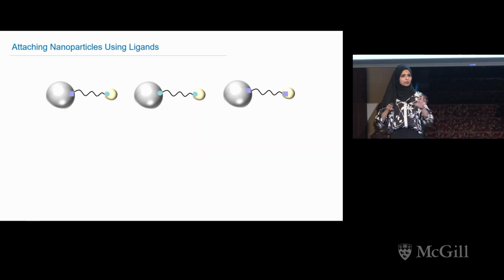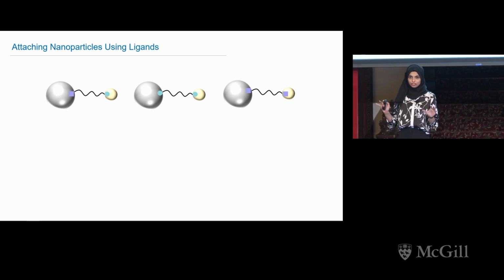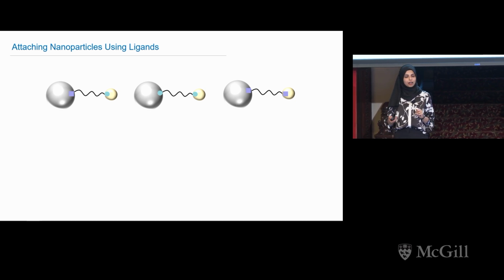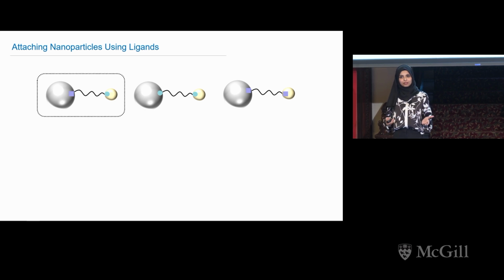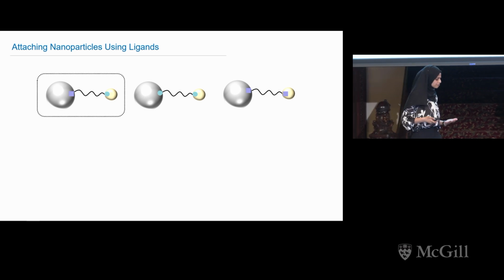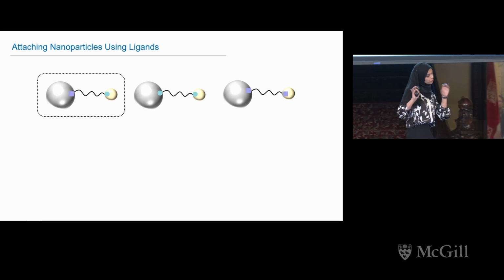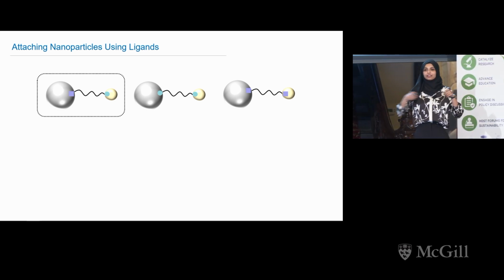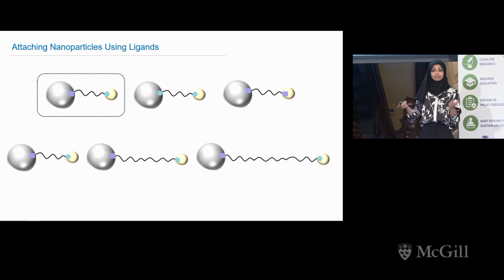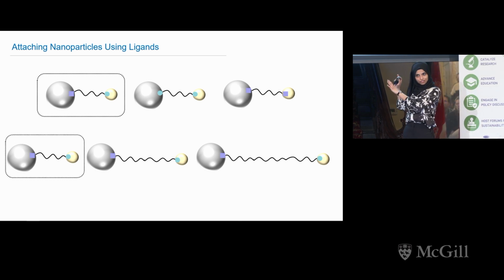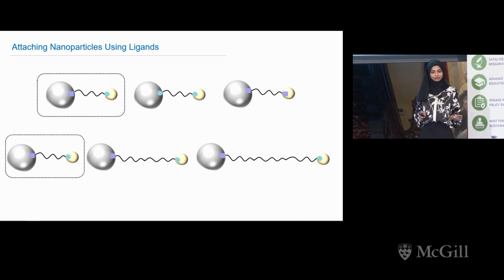I used different types of ligands with two different attaching groups, represented by squares and circles. So I had square and circle, circle and circle, and square and square. I found that the one with the square and circle performed the best. Next, I thought, if I keep the attachment group constant, what would happen if I vary the length of these ligands? I found that the shortest one performed the best. So this was kept constant for the next round of experiments.